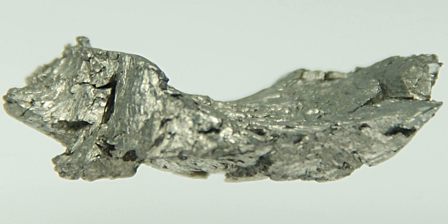Gadolinium possesses unusual metallurgic properties, with as little as 1% of gadolinium improving the workability and resistance of iron, chromium, and related alloys to high temperatures and oxidation. Gadolinium is paramagnetic at room temperature, with a ferromagnetic Curie point of 20 degrees Celsius. Paramagnetic ions, such as gadolinium, enhance nuclear relaxation rates, making gadolinium useful for magnetic resonance imaging (MRI).